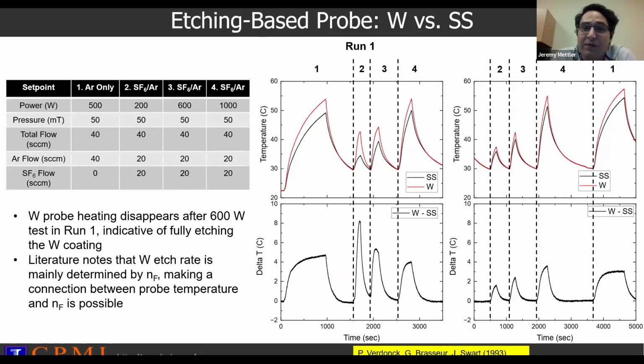We're in a very strong etching environment, so why not try to measure, instead of a recombination reaction, which fluorine is particularly bad at, an etching reaction instead, which is also an exothermic process. Here we did some initial investigations with tungsten, which is readily etched by fluorine. In run 1, which is argon, we see the probes read relatively close to each other, a few degrees separation. In run 2, we see a very strong temperature response from the tungsten compared to following runs.